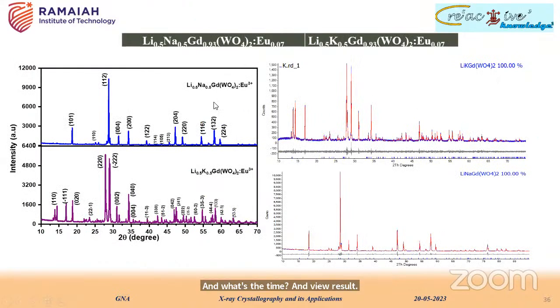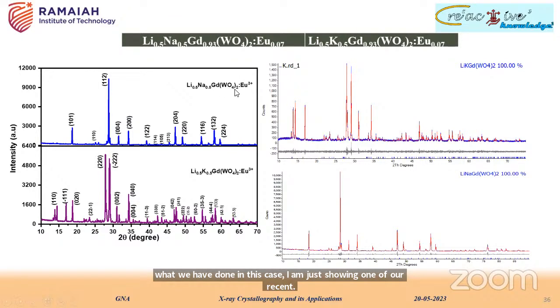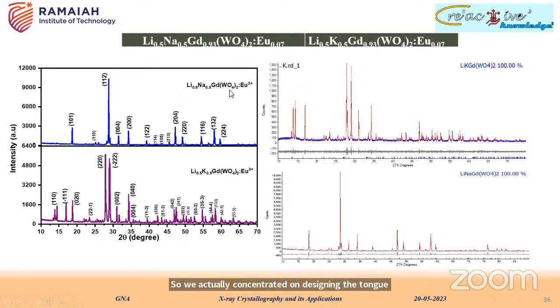And another thing is you can actually study the structure of the material also using this technique. So what we have done in this case, I am just showing one of our recent works. We concentrated on designing the tungstate material, gadolinium tungstate material. We have just incorporated sodium and potassium. So it is lithium sodium gadolinium tungstate, and another one is lithium potassium gadolinium tungstate.